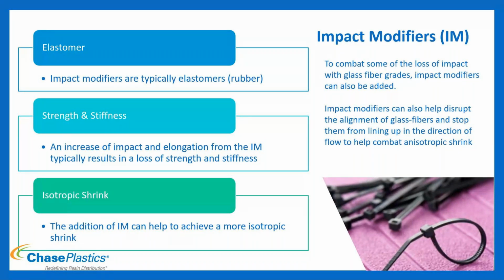So glass, you increase your stiffness and strength. You typically lose your elongation and impact. Impact modifiers do the opposite. They're typically made of an elastomer, some form of a rubber, with a TG well below room temperature. So they're very flexible, very high impact. And so when you add them to your product, you increase your impact and elongation.